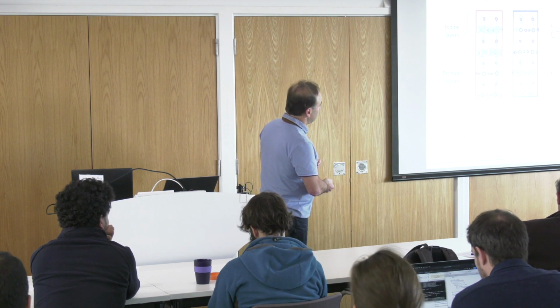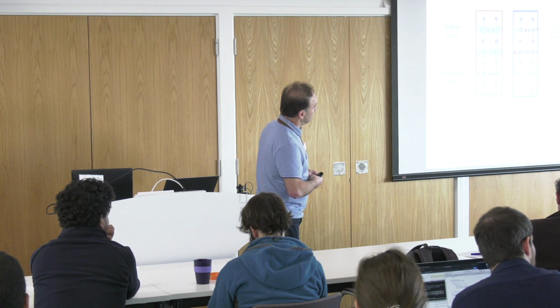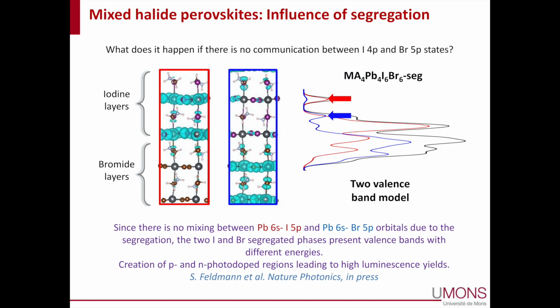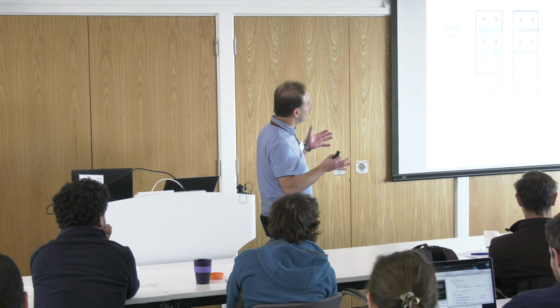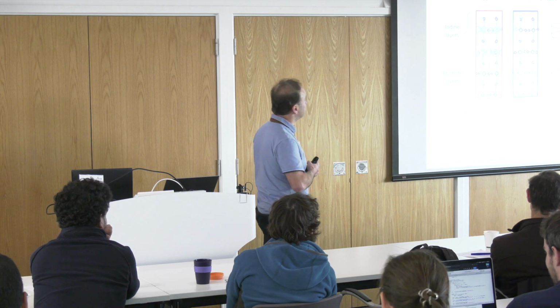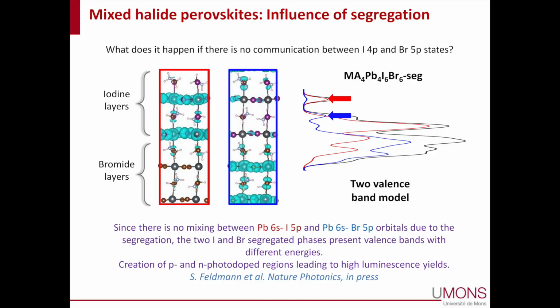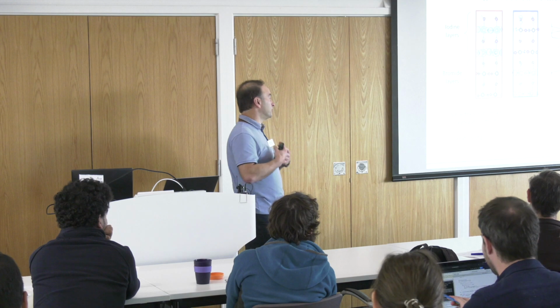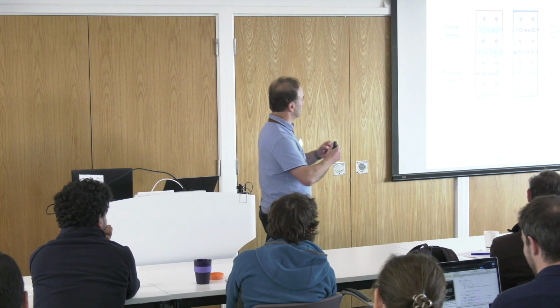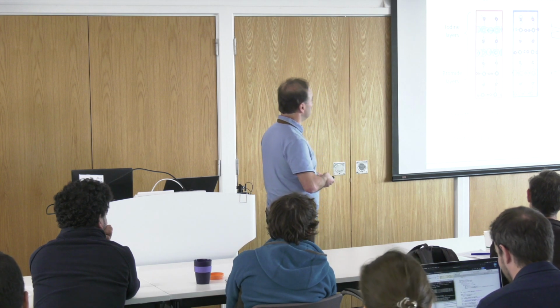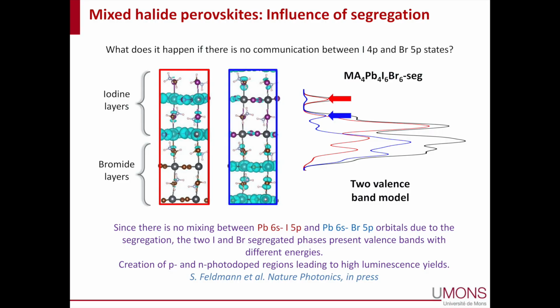Now, between parentheses, this is something that we discovered recently, also in collaboration with folks in Cambridge, with Felix Deschler and others: this separation drives the formation of doping domains, and the formation of those physically separated doping domains is responsible for a change in the recombination and an increase in the luminescence quantum yield when you go from pure iodine to mixed iodine, and then to mixed cations as well, because those mixed organic cations help you to get this phase segregation. So phase segregation is not necessarily a bad thing in those systems, at least in terms of the photoluminescence emission.